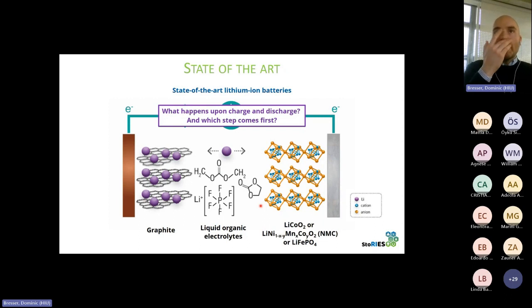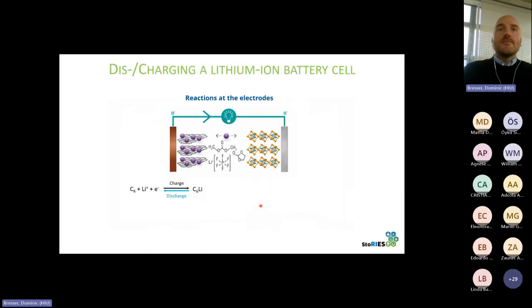Just a very quick excursion to talk about what happens upon charge and discharge, and which step in fact comes first in such a battery cell. If we think about the reactions at the electrodes, we stick to graphite, which is abbreviated here as C6. Then we have lithium-ion intercalation into the graphite structure, in between the graphene layers that you can see here, upon charge, and upon discharge the lithium ions move out again into the positive electrode.